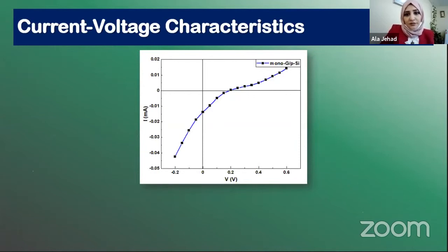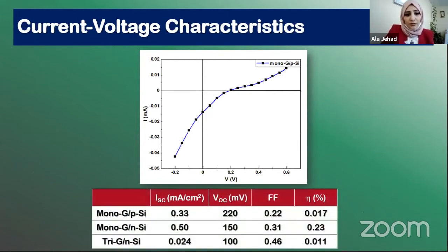The last result is current voltage characterization. We can see here the first for monolayer graphene on P silicon. Here we can see the efficiency of the cell. When we use P-type silicon, we got very poor efficiency, 0.01, which is something normal when we use P silicon because the majority carriers are holes. And for N-type silicon, the best efficiency we got is 0.2 when we transfer only 1 layer of graphene.